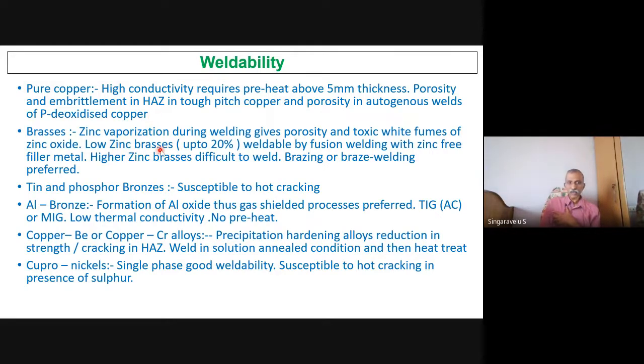Right? Low zinc brass, that is up to 20%, is weldable by fusion. And the caution is that a zinc-free filler metal has to be selected. That is the requirement. Normally, brazing is preferred for these brasses, or braze welding. Okay. Higher zinc brass is very difficult to weld. This is the best method. Tin and phosphor bronzes: very high hot cracking occurs. Prone to hot cracks because these form low melting constituents.